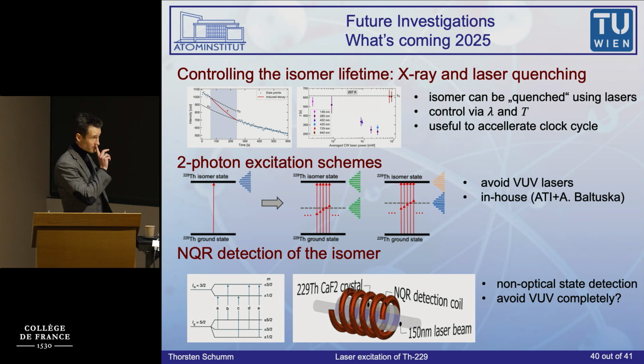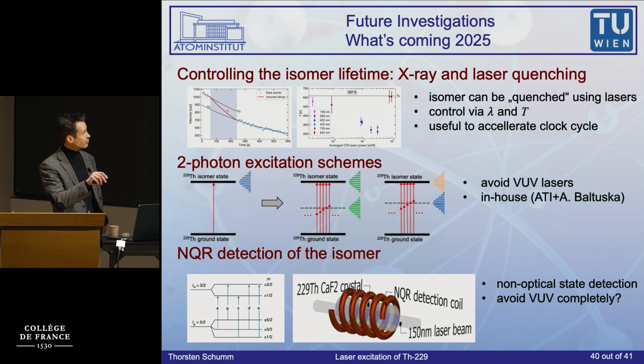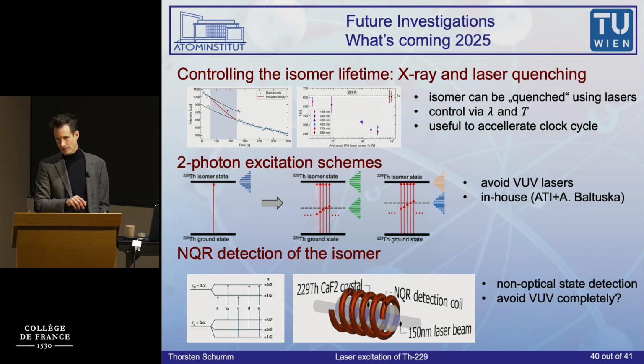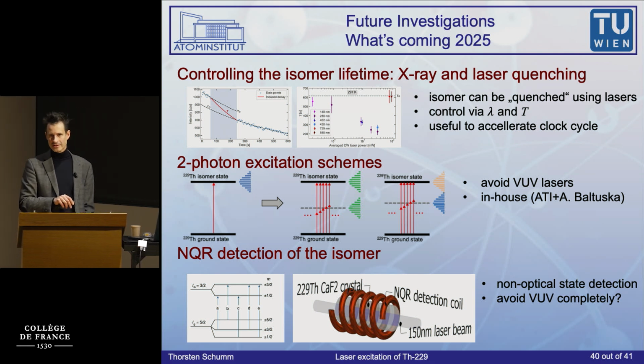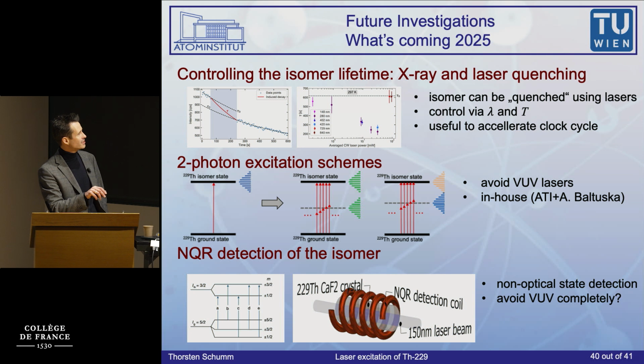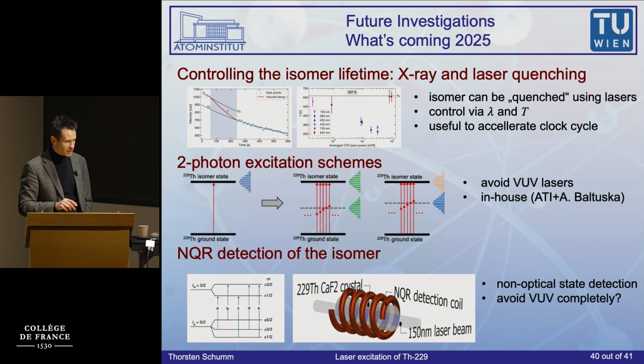The last thing I would like to show is, I showed you this quadrupole structure, and we're currently probing these transitions optically. And I said these are 2 petahertz transitions. These splittings here are on the 200 to 300 megahertz level. This is radio frequency. That's simple. We could just play with these levels by putting a coil around that and drive these transitions here, and then we would maybe have some sort of a non-optical readout scheme that could also help us to maybe speed up the system. This is a known technology.